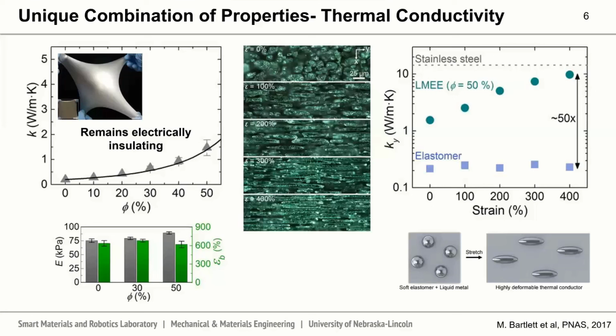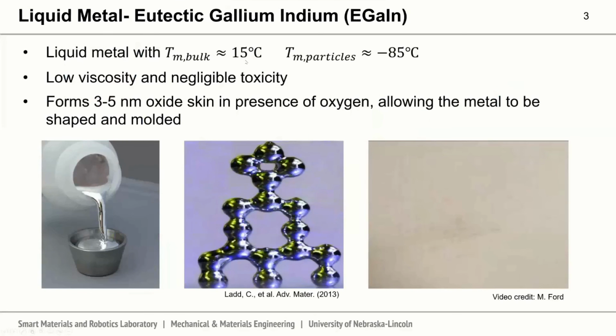One of the really critical temperatures is actually the minimum, so when does it transition from liquid to a solid? In its bulk state, its melting temperature is around 15 degrees Celsius. But if we begin to put this into particles, we get a supercooling effect which suppresses this to negative 85 Celsius, which is around or after the limits of most of these elastomer matrices we're currently using, where we get a large increase in stiffness from the silicone before we do the change from liquid to solid state.